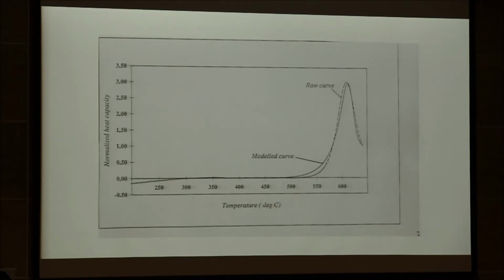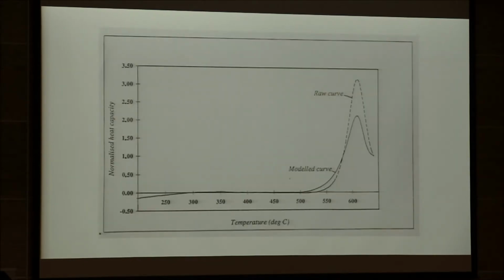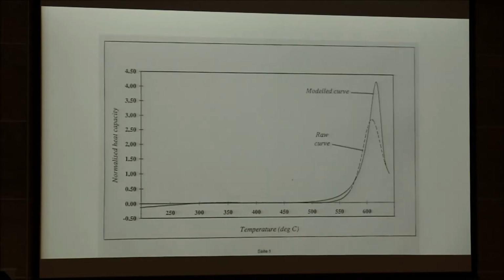All right, so we fit these curves. This is just to give you a taste of how accurately we can do it. This is the raw curve dashed and the model curve solid, so we consider that a very good fit. And if we change it by a factor of 2, which sounds like a lot for a physical scientist, but remember this is a logarithmic variation of viscosity, then we miss it horribly, okay? We go the other way, we miss it horribly the other way. So we can do this much better than a factor of 2.